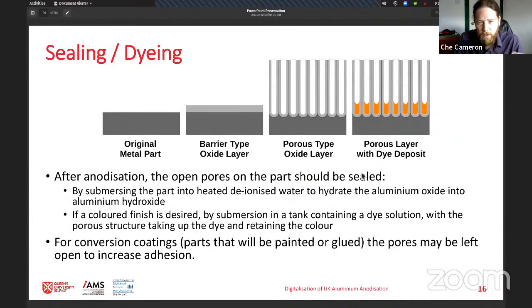Once you have your porous layer grown and your oxide is finished, you'll take the part out of the tank. But at this stage, that oxide layer is vulnerable in some respects. It's described as open. So the pores will basically uptake anything around them very readily. And this is actually desirable, but you need to do something about this. So if you want a plain oxide coating, you can just drop the parts into deionized water, and that'll hydrate it and seal the pores.